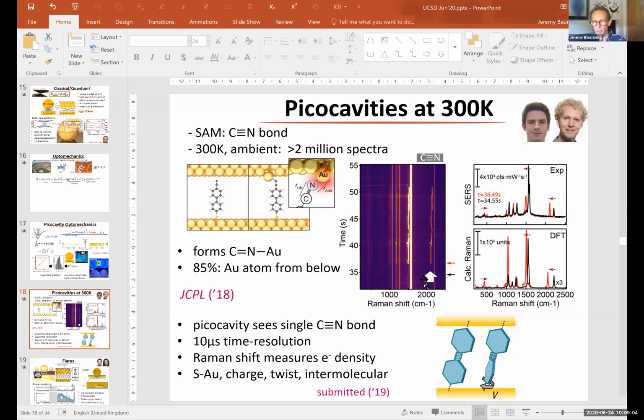And we can tell that because if we look at Raman spectra, in this system here, we've collected millions and millions of Raman spectra. And most of the time, we just see these lines here, right? Which is just what you expect from the normal gap. It's only very occasionally we see this extra thing happening. And that matches what happens when a single gold atom gets pulled out by about half of its diameter, right? So what happens, and the model sort of shows it works well, is that we get an extra optical field here. And because the Raman scattering strength goes as the optical field to the power 4, then the extra sort of 3 to 5-fold enhancement here gives you a 100-fold enhancement of the Raman scattering from that bond. And that's why the strength here is about the same as all the other 100 molecules that we're seeing in the gap. So this is from 100 molecules, and this is from 1 molecule. And it's coming from this enhanced optical field here.